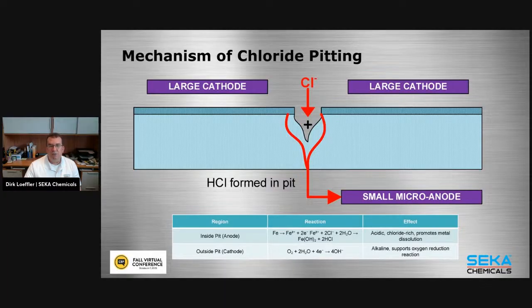Another illustration of how this works is that it's really an electrochemical process. The metal surface presents a large cathode, and we have our little pit here, which creates a small micro anode. Inside the pit, in our anode, this chemical reaction takes place, which, amongst other things, always produces a little bit of hydrochloric acid. So we have an acidic, chloride-rich environment, which unfortunately further promotes the metal dissolution. That means this pit's going to get deeper, and this process is going to get more and more pronounced, and it's going to keep breaking down our stainless steel.